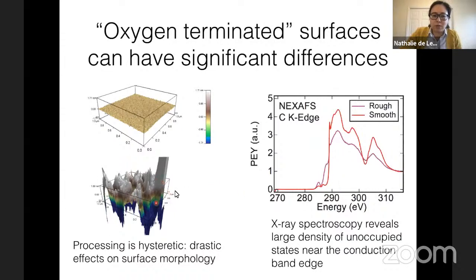So if we now take this rough surface and the smooth surface and put them in this NEXAFS spectroscopy, we can see that the rough surface has this enormous density of unoccupied trap states that are near the conduction band edge. So what you're looking at here is everything. This is the exciton peak in diamond. Everything to the right is the band structure of diamond. Everything to the left really just shouldn't be there. So these are basically trap states that can serve as sources of magnetic and electric field noise.